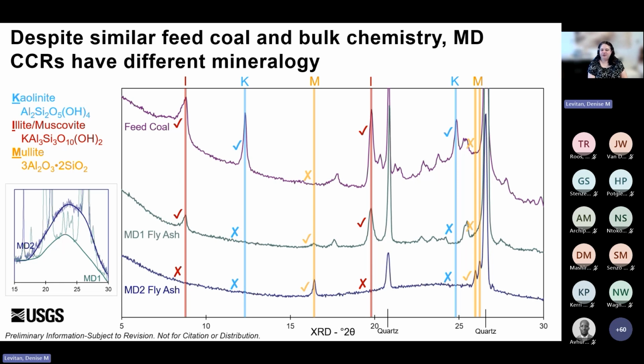So then another feature that we can see from the X-ray or the XRD pattern, if we look at a different scale here, so this is 15 to 30 degrees 2 theta, whereas that here is 5 to 30, so it's kind of squished up, is we can see these broad humps that are indicative of amorphous content. In this case, it's probably amorphous aluminosilicate glasses. And so what this is where you have heated minerals that are melted, and then they sort of fall within the boiler in little droplets, and they are cooled too quickly to form organized crystal structures. So they don't really have peaks within the X-ray diffractograms. They just have this broad hump. And you can see it sort of here in MD2, it's pretty distinct, whereas in MD1, it's pretty minimal.